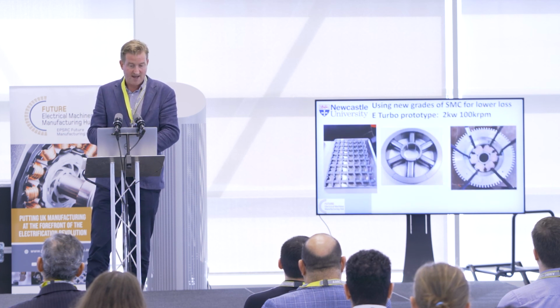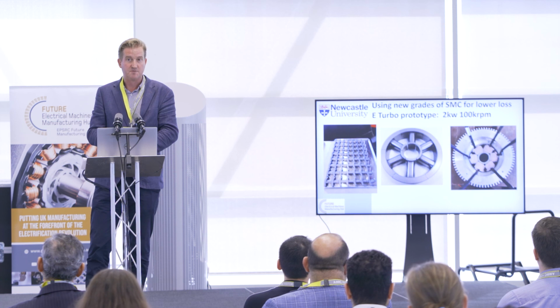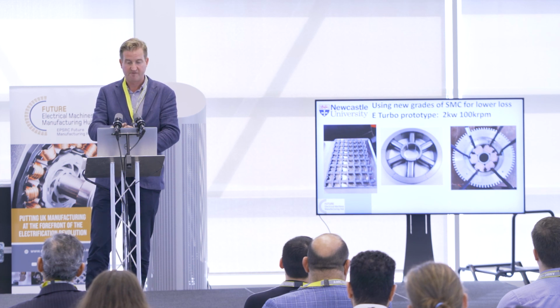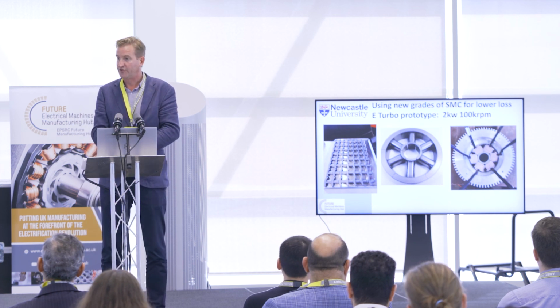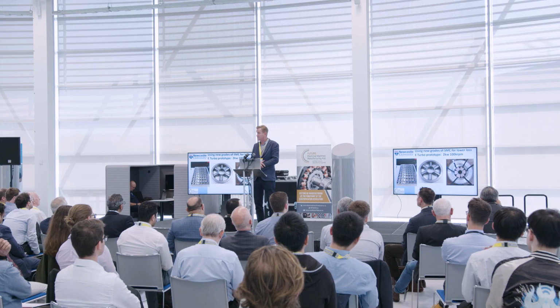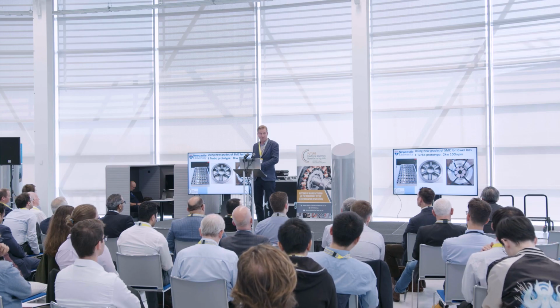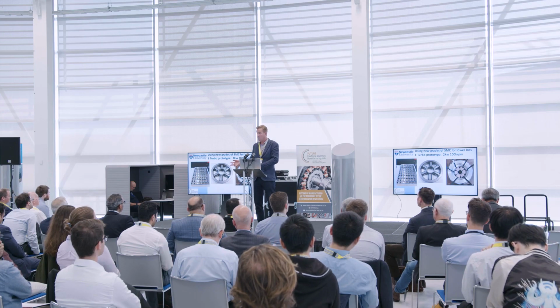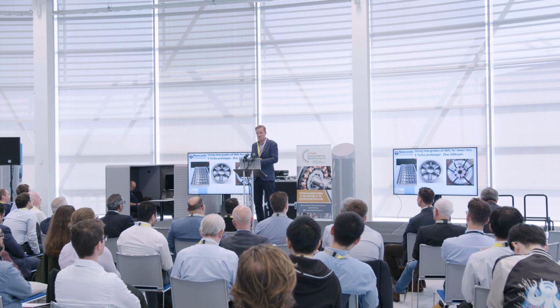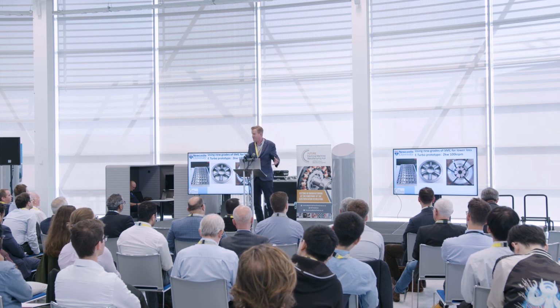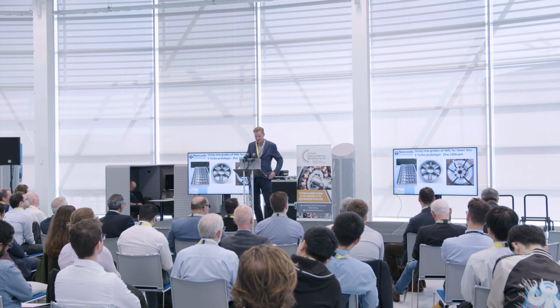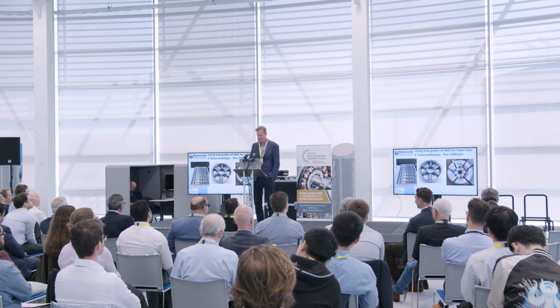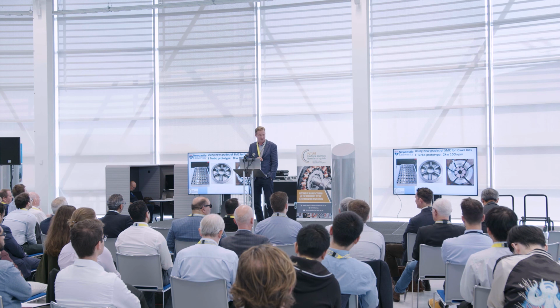Recent work we've done is on higher speed machines, running up to 100,000 RPM. That's using the newer grades of soft magnetic composites. We're finding that the losses in this material at these high frequencies is lower than a reasonable lamination, certainly not some of the really exotic Japanese laminations that we may get, but this is looking quite good, and quite nice in terms of losses.